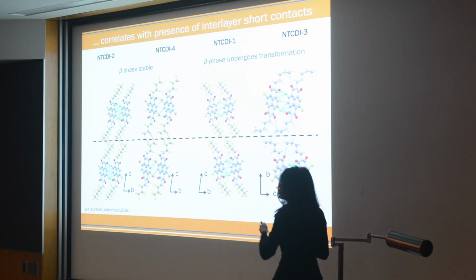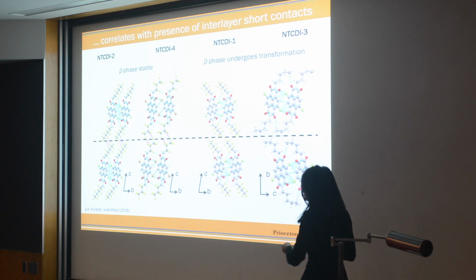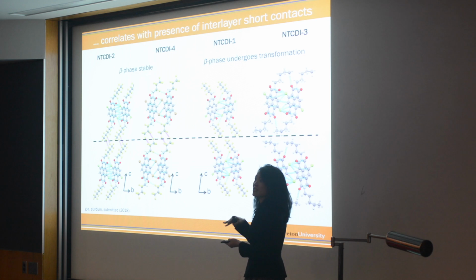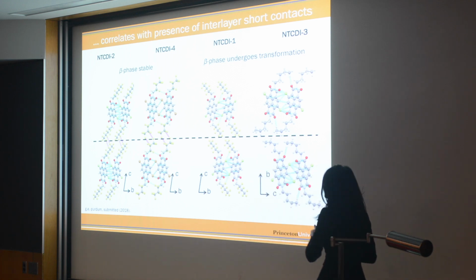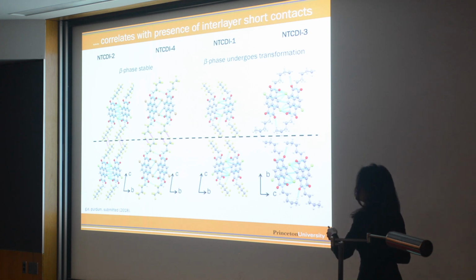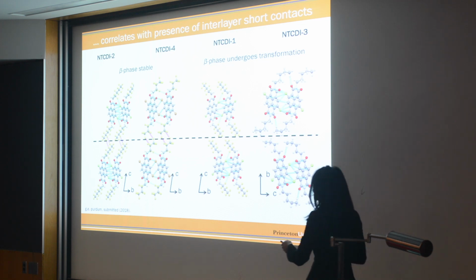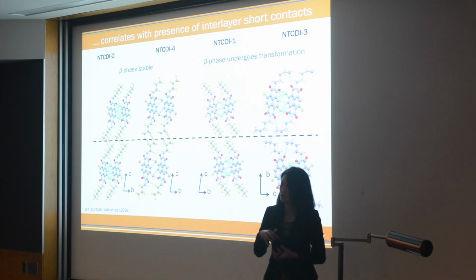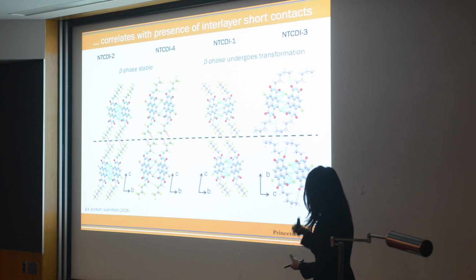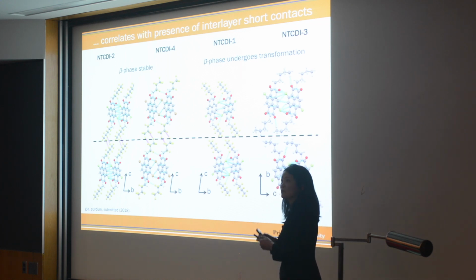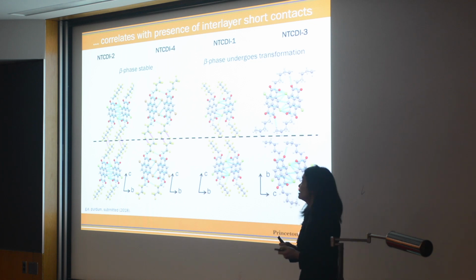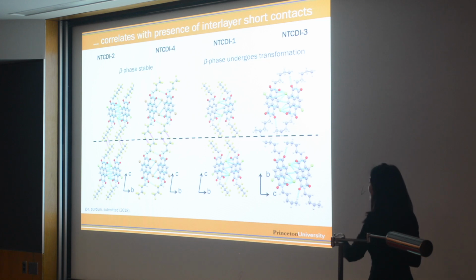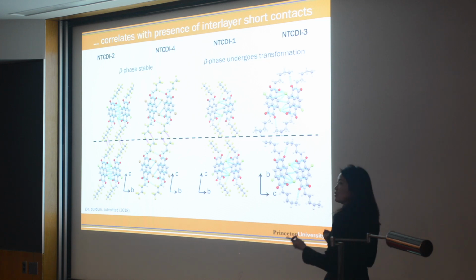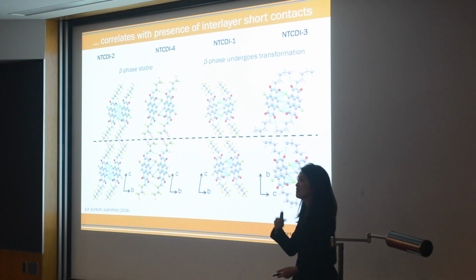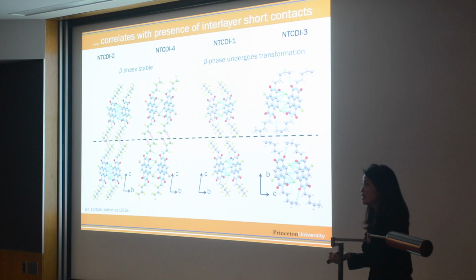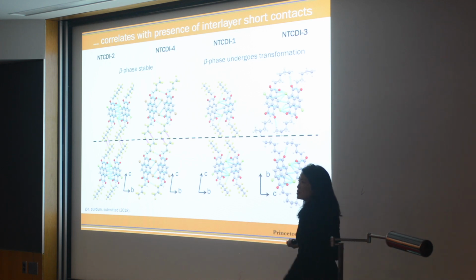Now, what's different between these two pairs is that with NTCDI2 and NTCDI4, we see these short contacts between molecules in adjacent layers. In NTCDI1 and NTCDI3, we don't see these short contacts between adjacent layers. So we hypothesize that these short contacts are what locks the structure in place, and it precludes NTCDI2 and NTCDI4 from transforming out of the beta phase into the alpha phase. Whereas in NTCDI1 and NTCDI3, we don't have these short interlayer contacts. And because we don't have these short interlayer contacts, we can transform out of this beta phase into the alpha phase.